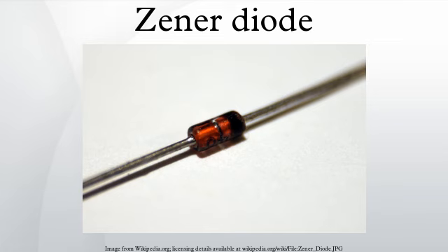The breakdown voltage can be controlled quite accurately in the doping process. While tolerances within 0.07% are available, the most widely used tolerances are 5% and 10%. Breakdown voltage for commonly available Zener diodes can vary widely from 1.2 volts to 200 volts.